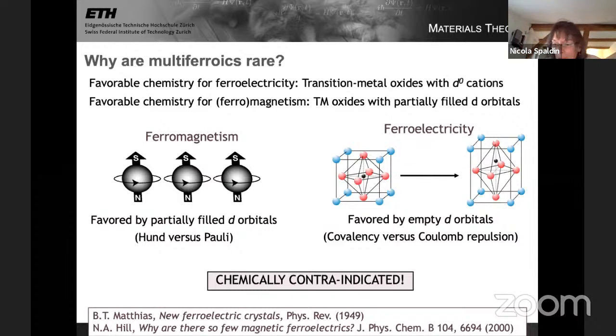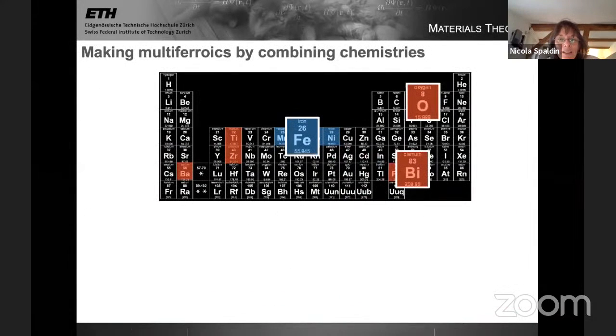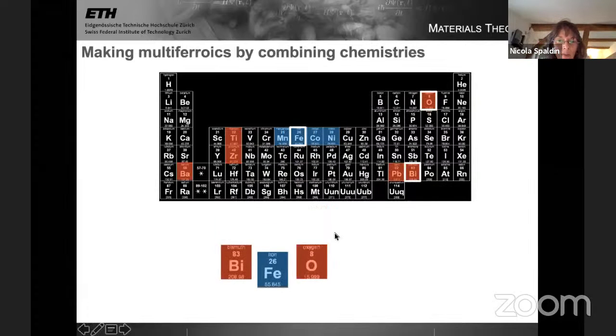Okay, so let me show you an example then. The simplest possible way of making a multiferroic, and I should say there are now very many clever ways, Daniel has really introduced some. I'm going to give you one, and if there's time, maybe two examples of really non-clever ways of designing a multiferroic. And that's basically by just combining the chemistry. So taking a transition metal with its d electrons and then introducing the ferroelectricity in a different way than using a D0 cation. The example I want to show you is bismuth iron oxide, bismuth ferrite.